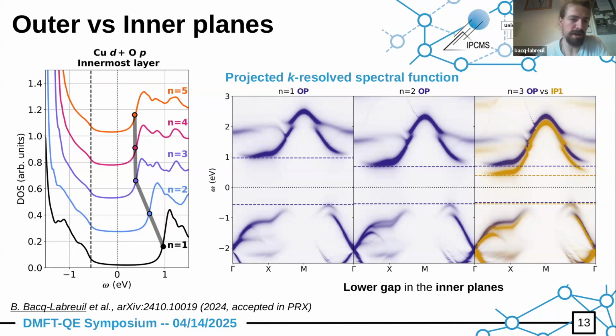Right, so this further reduction in going from the two-layer compound to the tri-layer compound is basically due to the presence of inner planes. And here there is no doping whatsoever, so it's really intrinsic to the compound that the inner plane seems to have effectively a little less correlation than the outer planes.